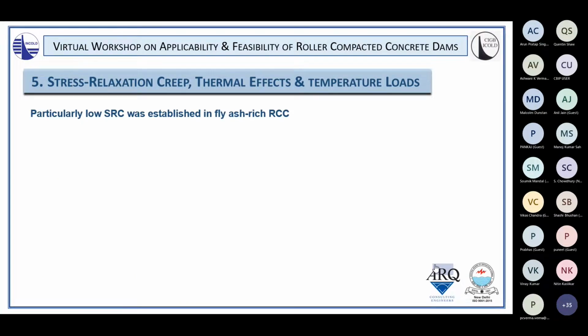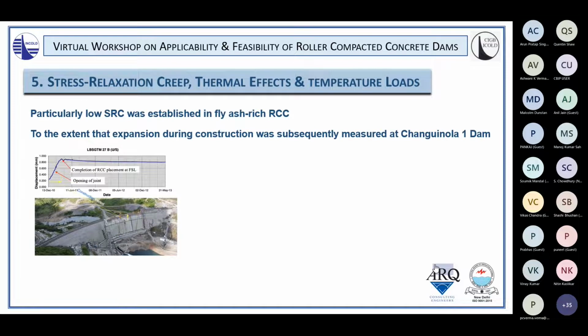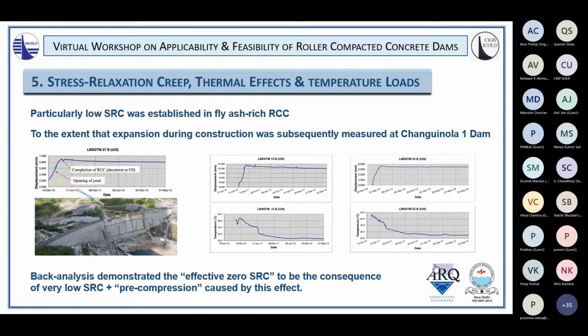Particularly low stress relaxation creep was established in fly ash rich, high workability RCC, to the extent that expansion during construction was actually measured at Changuinola 1 Dam. So the graphics shown here were measured at strain gauges across the joints at an elevation approximately 10 meters below the crest level, a little bit more, and on the upstream side, so several meters from the upstream face. What was established was that for the placement above those gauges, a linear expansion on those gauges was determined, which occurred until the horizontal construction was completed. So in other words, at the level of the spillway crest, it just stopped and disappeared.